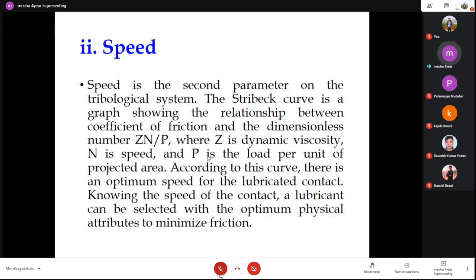Speed is the second important parameter in the tribological system. The Stribeck curve is a graph showing the relationship between the coefficient of friction and the dimensionless number ZN/P, where Z is the dynamic viscosity, N is the speed, and P is the load per unit of projected area. According to this graph, there is an optimum speed for the lubricated contact. Knowing the speed of the contact, a lubricant can be selected. So Z, N and P are very important parameters from the Stribeck curve, where Z is the dynamic viscosity, N is the RPM, and P is the projected load.